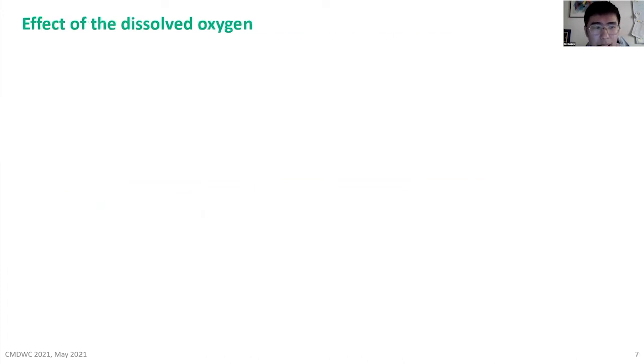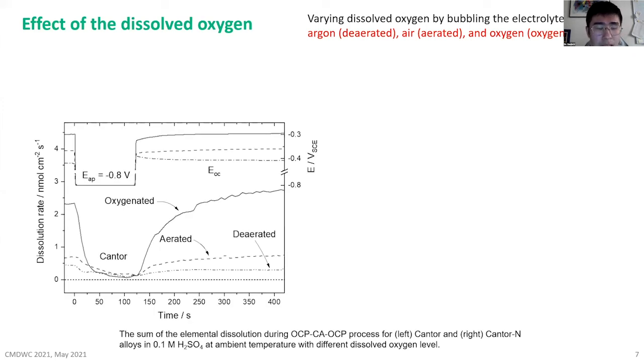So in this slide, we investigated the influence of dissolved oxygen. As I said before, we are interested in its influence. So we varied the dissolved oxygen in the solution by bubbling the electrolyte with argon, air, and oxygen. They are referred to as the deaerated, aerated, and oxygenated solution, respectively. The first curve shows the results of the same experiment performed on the Cantor alloy in these three electrolytes. We can see that when we increase the dissolved oxygen content in the solution, we increased the open circuit dissolution for the Cantor alloy, as well as the open circuit potential.